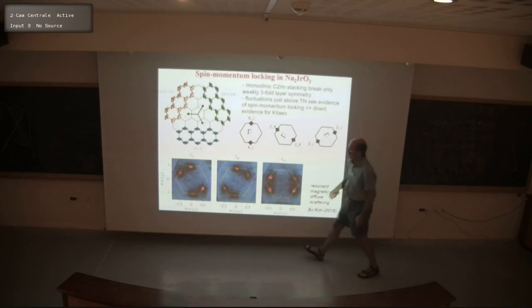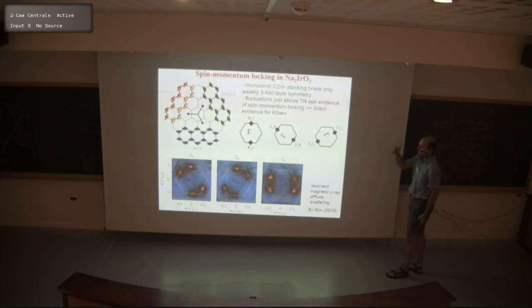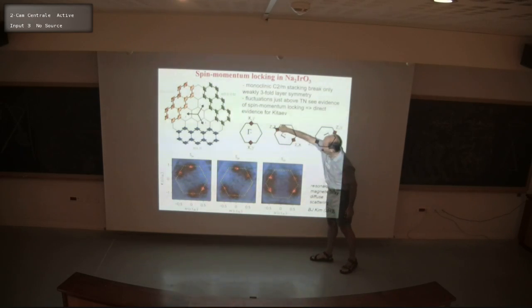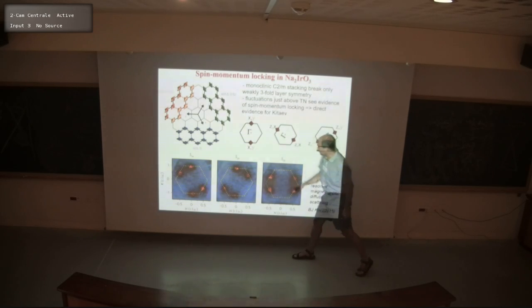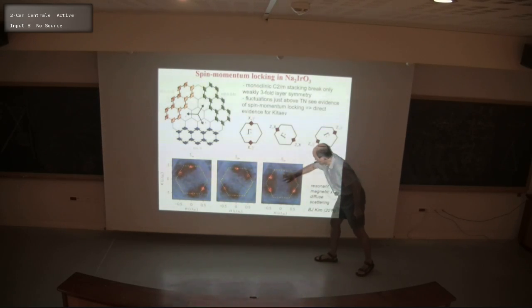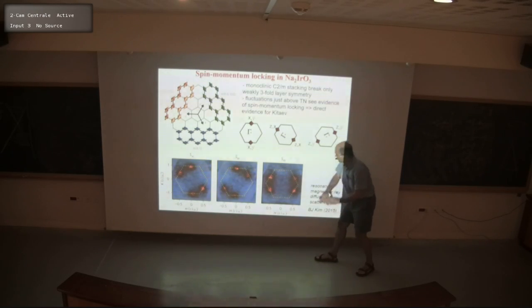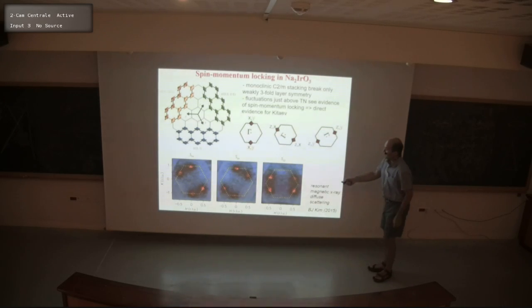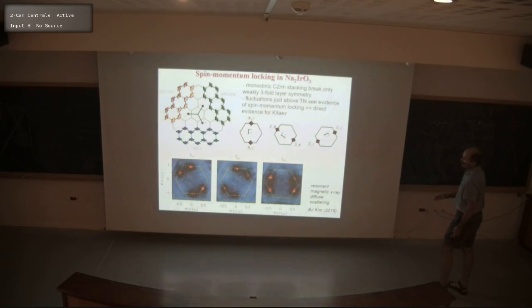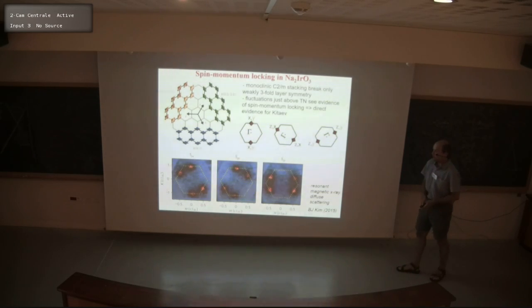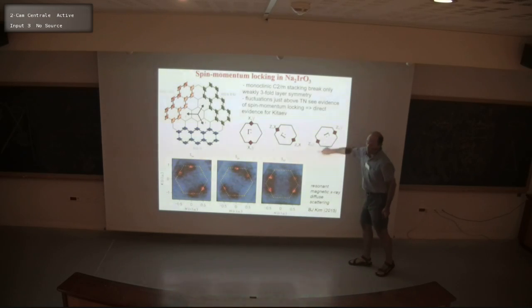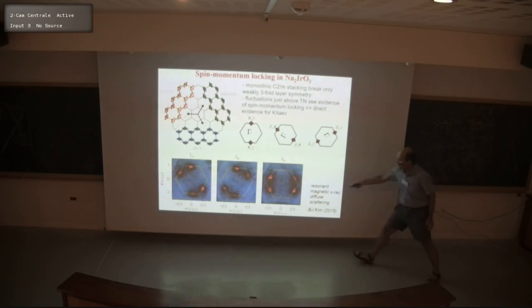And then what's interesting is that the polarization of the fluctuation is linked to the moment direction. So for example, the Z spin directions would be expected to fluctuate at these two positions and also these two positions, but not at the vertical positions. And indeed, ZZ scattering has spots, intense spots that are finite in momentum at these positions and not at those ones. And the other polarizations are also obtained by rotation. So this is a feature that very directly illustrates the momentum and spin locking. So spin fluctuation along a certain direction is linked with the moment. So this could never happen in a Heisenberg system where the system would fluctuate between all of these three with no polarization dependence. So there will be spots everywhere with 120-degree symmetry.